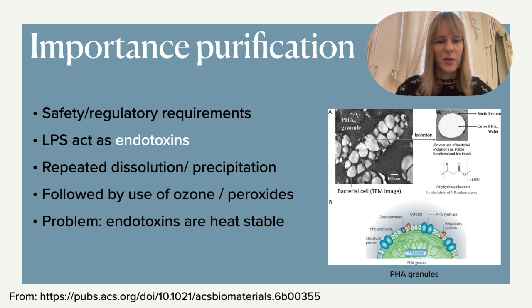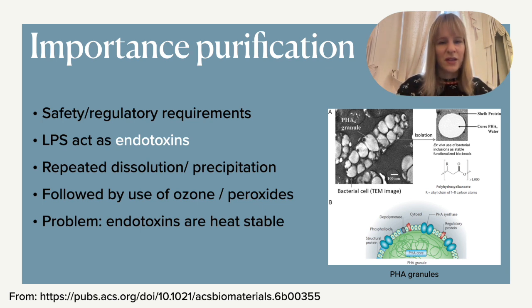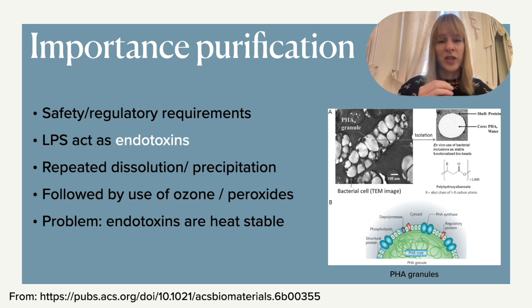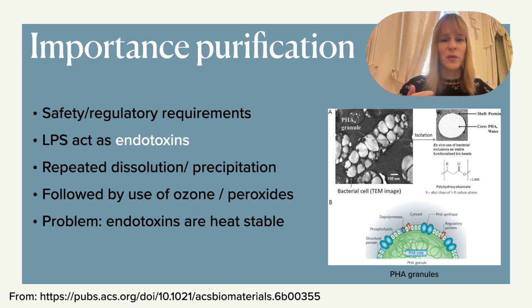In this image you can very clearly see PHA accumulating in the cells, giving a real sense of how much is present. Beyond extraction, the final application also requires consideration of safety and regulatory requirements — specifically endotoxins. These are lipopolysaccharides found in cell membranes that can act as endotoxins. The problem is that they are heat-stable, so autoclaving is not suitable for removal, and they can invoke immune responses. Biosafety regulations require that you demonstrate, using sensing techniques, that endotoxins have been removed before the product can be used. The tolerated amount depends on the application — construction versus food-contact packaging, for example, have very different regulations.